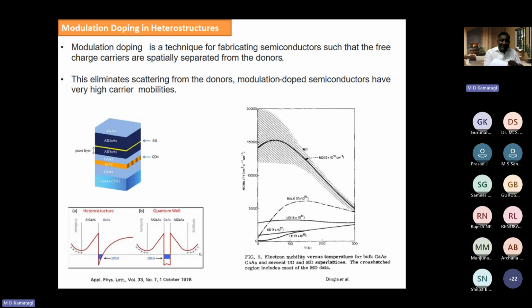And when we sandwich gallium arsenide between two aluminum gallium arsenide layers, effectively we are joining two heterojunctions. When we join the two heterojunctions, it forms a well-like structure, and that we call a quantum well. This is the gallium arsenide, typically of the order of 1 to 100 angstrom. Then we sandwich it between two aluminum gallium arsenide layers. If it is a heterojunction, only one aluminum gallium arsenide.